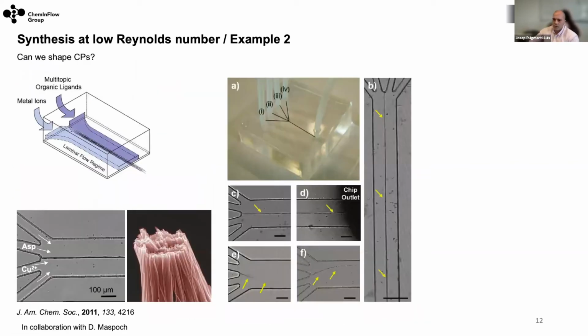So our next study was to accelerate reactions. This was already published by the group of Professor Daniel Maspoch. They published this in JACS, I think in 2010. They made a coordination polymer, and it took them some days to generate the nanofibers. So the idea here was to see if with microfluidics, we could accelerate the crystallization process. Well, this is what you can see here.